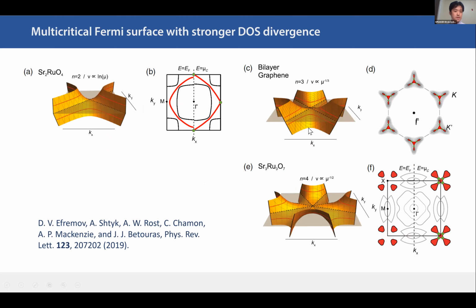In strontium ruthenate 214 material, we see a touching of two Fermi surfaces at the zone boundary, which gives rise to a divergence in density of states accompanied by the Van Hove singularity. And this log divergence is universal in two-dimensional materials with saddle point singularities, but more exotic phenomena happen when more than two Fermi surfaces touch at a point.